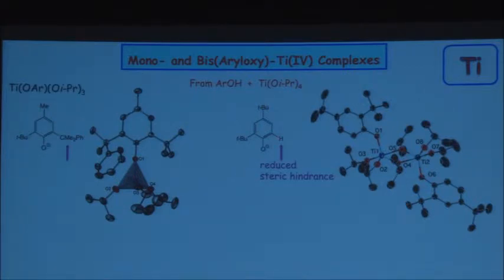But if you have in ortho position here to this group a small H compared to this bulky ligand, you don't get a mononuclear species. You get a dinuclear titanium, still oxidation state 4. It's not a redox reaction. Titanium remains titanium-4. But now we have a dinuclear structure with isopropoxide bridges. These OR ligands can be terminally bound, or can be bridging ligands. A great diversity, very versatile systems.